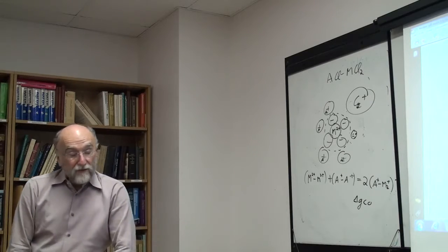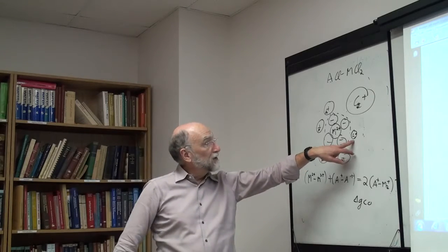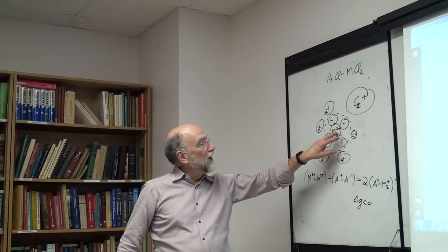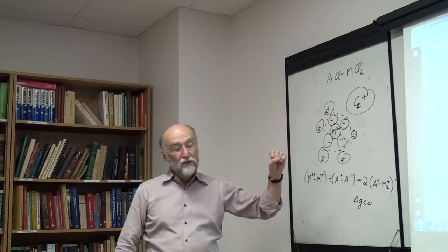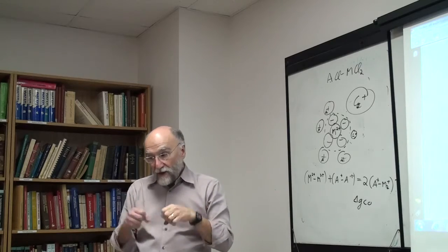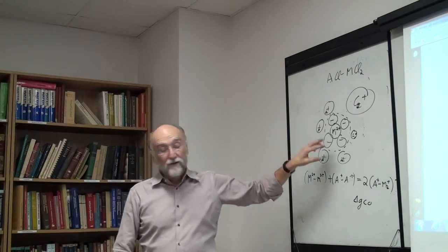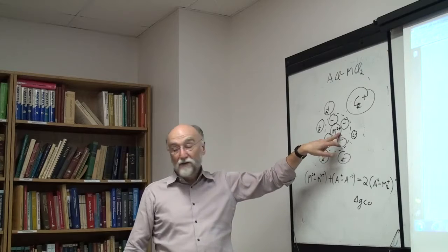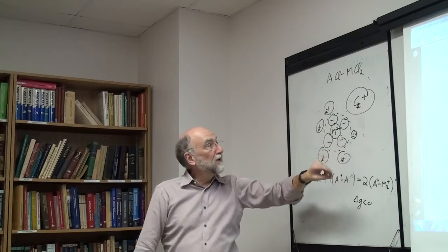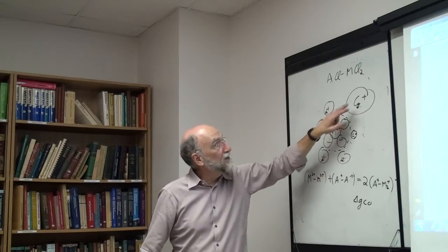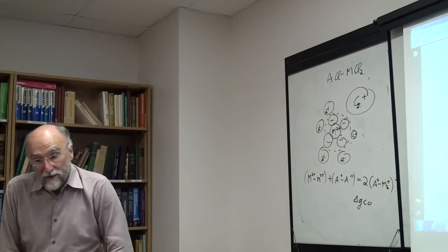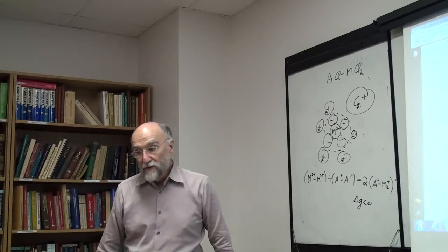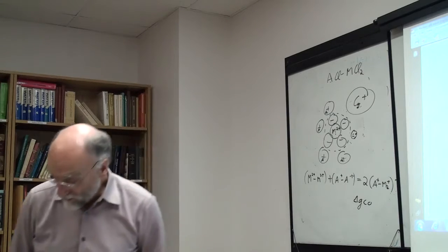So the stronger, the smaller, and the more strongly charged the ion is, like magnesium 2+, the greater is its tendency to form these complexes. The lithium is kind of competing with the magnesium for its own complexes. Cesium has no tendency to do that. That's how I like to look at it, with cesium and magnesium: it just maximizes your distance between your strong secondary interactions and keeps the magnesiums away from each other.